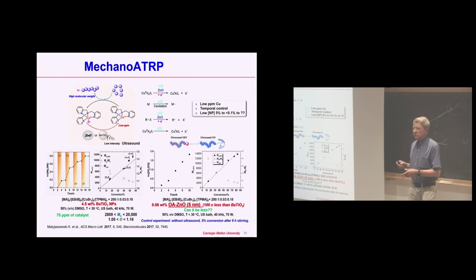An interesting extension of this electrochemical process is using piezoelectricity. There are some species, like barium titanate or zinc oxide, which generate a positive charge on the surface under ultrasound or mechanical forces, and in that case it can attract copper, and eventually you will have a reduction of copper-2 to copper-1, starting the reaction. So if you switch this piezoelectric effect, the ultrasound, off, there is no polymerization. On, off, on, off, on, off, and you can climb to whatever molecular weight you want with low dispersities.